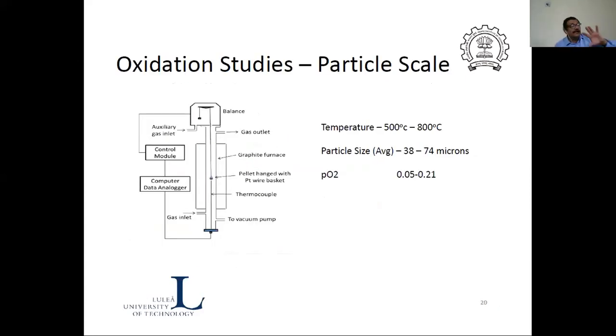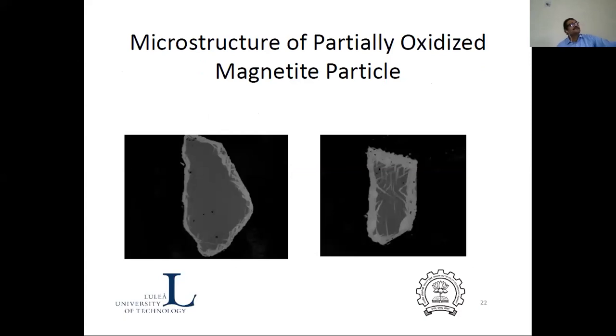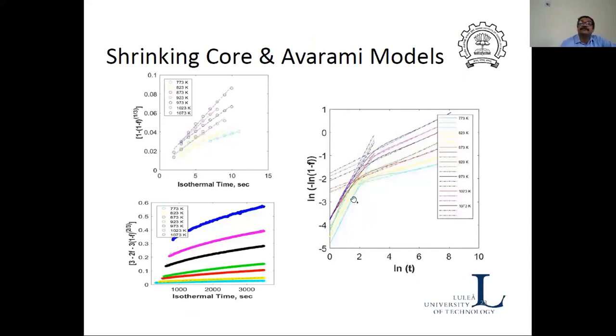Then, of course, this is one part where it is only sintering. Then we also went ahead with oxidation, where we conducted TGA experiments. I don't want to go into the details, but we did all those studies also. But I just wanted to tell you, we looked at single particles of magnetite inside the pellet, and we looked at the microstructure. For example, this is the way the hematite grows, the needles of hematite coming in. Again, we used the principles from phase transformation to understand this, and there is something called the Avrami equation. Some of you may be familiar, and we found that the Avrami equation fits so well. Again, these are experimental observations, and we were fitting with the Avrami equation. So that way we could describe the particle kinetics.